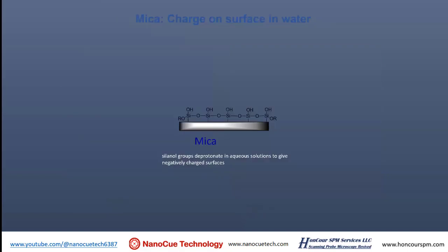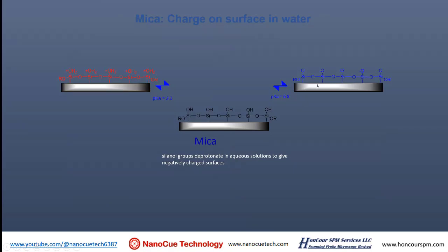Okay, let's talk about the charge on the surface of mica. Mica surface in neutral water is actually negatively charged because the hydroxyl loses a proton, and then the surface is negatively charged at a pH value of around neutral. 6.8 is neutral. In a very strongly acidic liquid, the surface will turn positive because in strong acid there are excessive protons, or hydrogen cations, and they will be attracted to hydroxyl and adhere to it. The surface becomes positive. So in strong acid, pH 2 point something is very strong acid, you can dissolve a lot of things in it. But in clean water, it's negative.